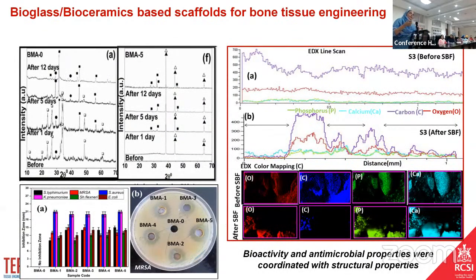And then, as I explained earlier, you can see on the left side the XRD graph, used to identify whether there is any hydroxyapatite formation on the surface of the material or not. You can see before, after 1 day, after 5 days, after 12 days, in SBF. Before is what I prepared in the lab, and after 1 day is the XRD of the sample after 1 day in SBF. Is there any structural change? Is there any ion release? What is the effect? It's bioactive.